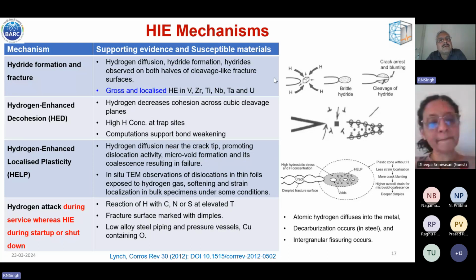Usually, the moment people charge it, they dip the sample in liquid nitrogen so that hydrogen does not escape. Second, you can have an FCC coating, like nickel or copper, on the sample so that hydrogen does not escape. And of course, computational solutions are there for hydrogen enhanced decohesion, the second mechanism. Computational support has shown that yes, bond weakening takes place if dissolved hydrogen is present.